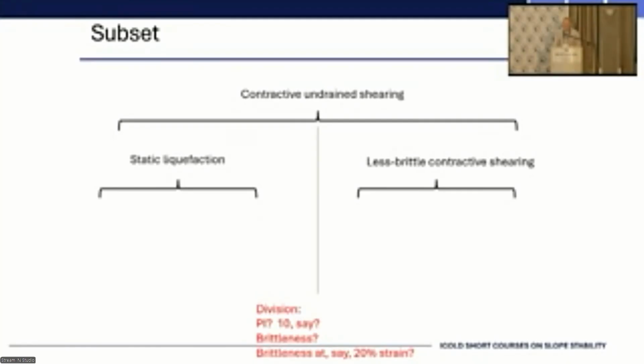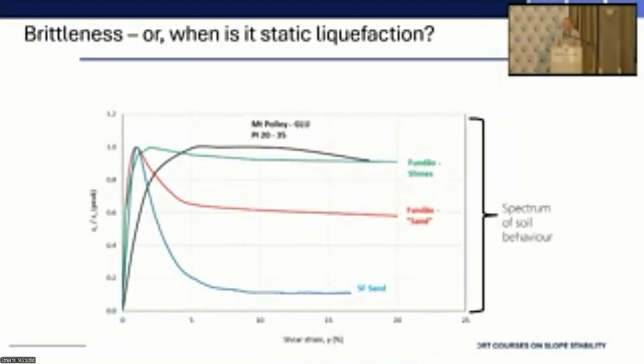I had a paper presented at a conference in Mexico about 5 weeks ago, and I'm waiting for the clearance to circulate it. But that looks at post-peak behavior as well as the brittleness index to try and perhaps suggest another measure called the susceptibility index, which captures both those aspects, the strength loss and the strain over which it occurs. But we get this complete spectrum. We get the Fundão and the Mount Polley material from forensic reports. We get the sand from Fundão. We get, as a comparison, that silica fine sand again. And these are all isotropically consolidated.